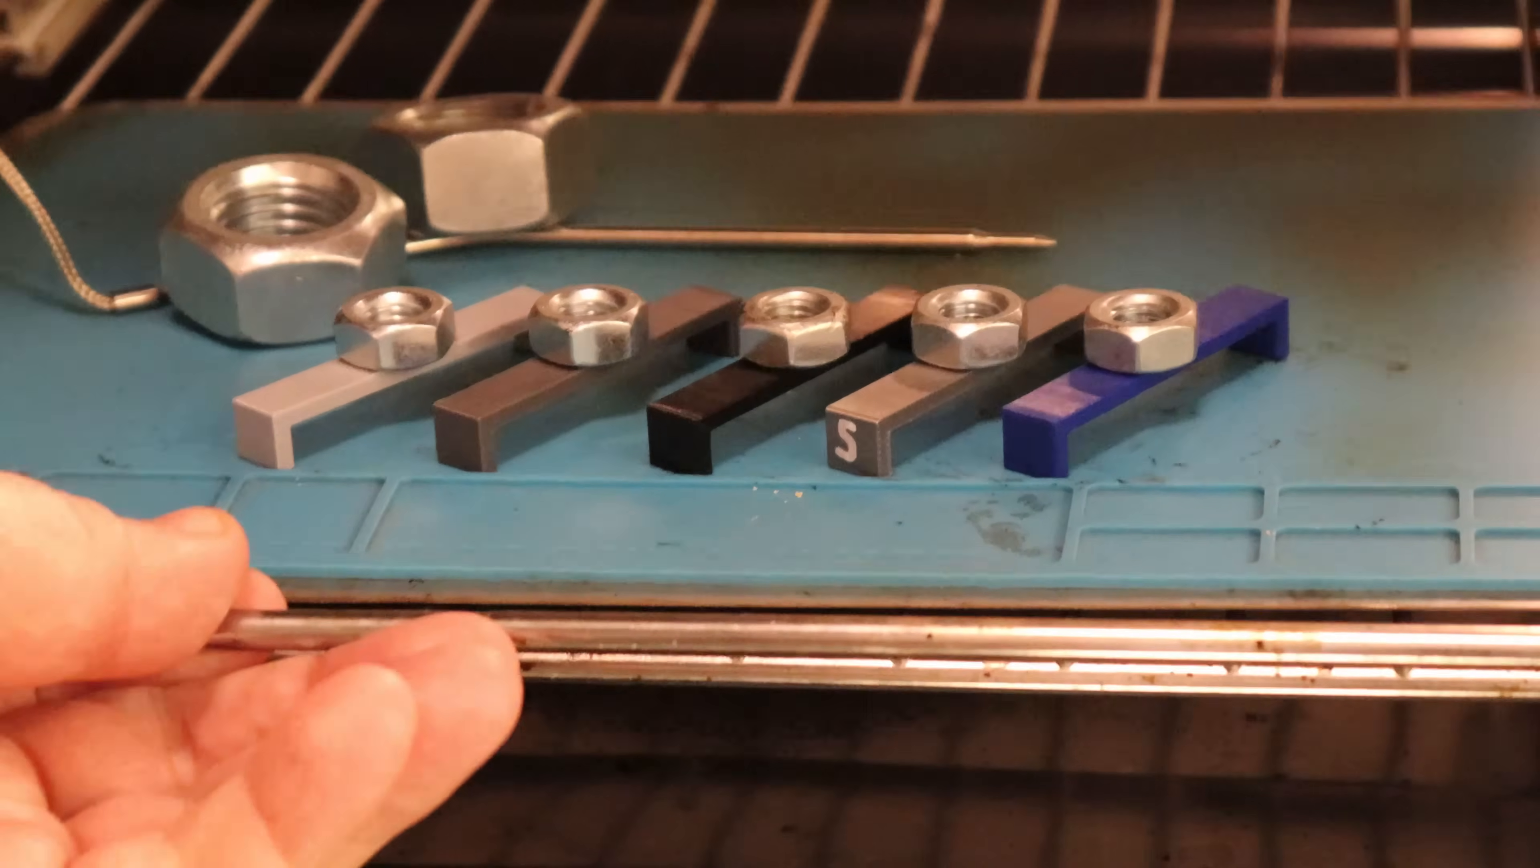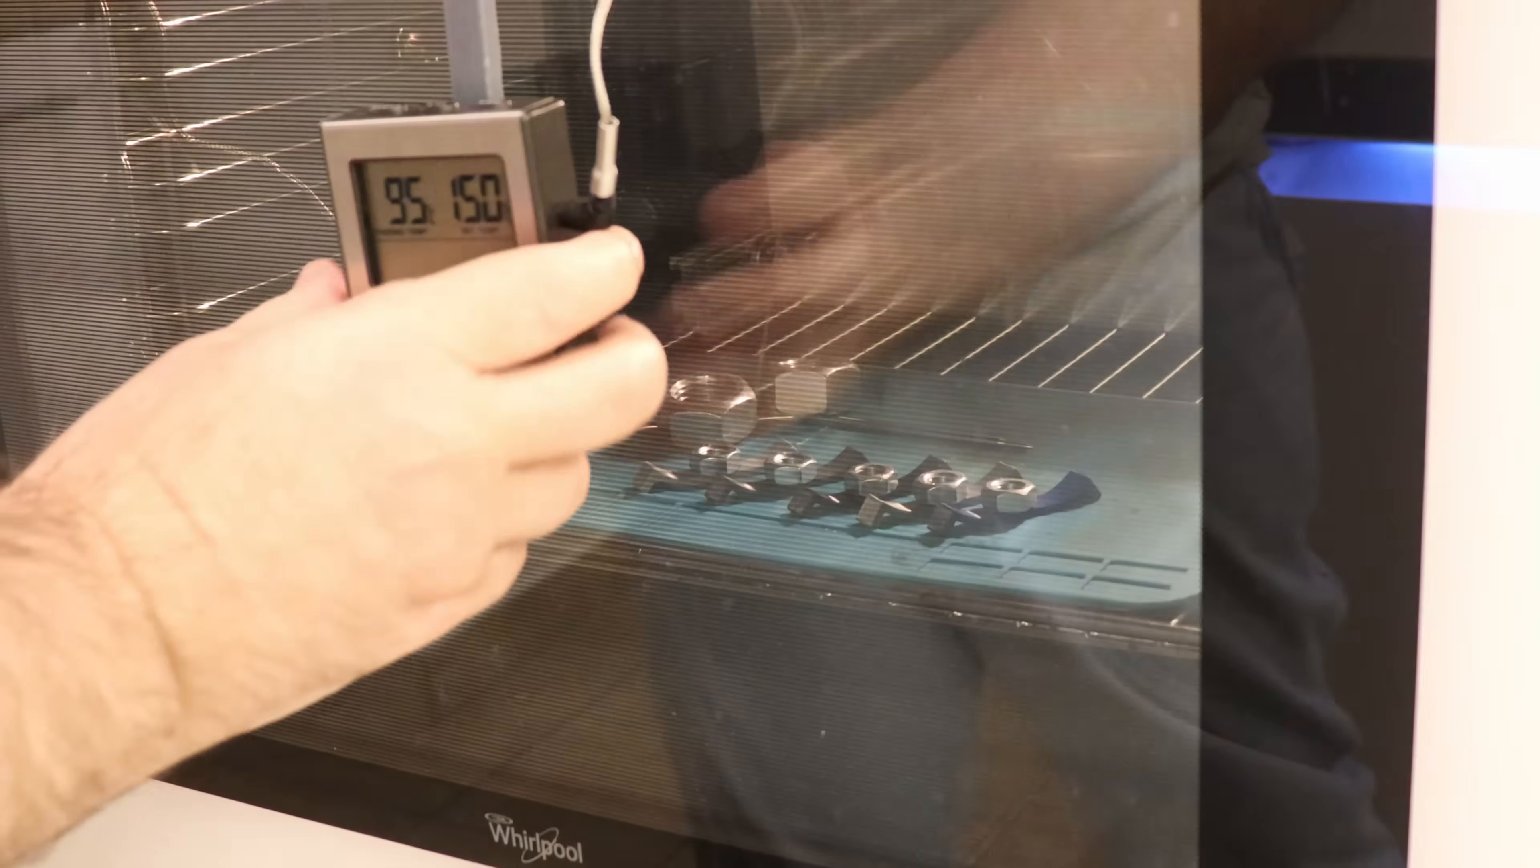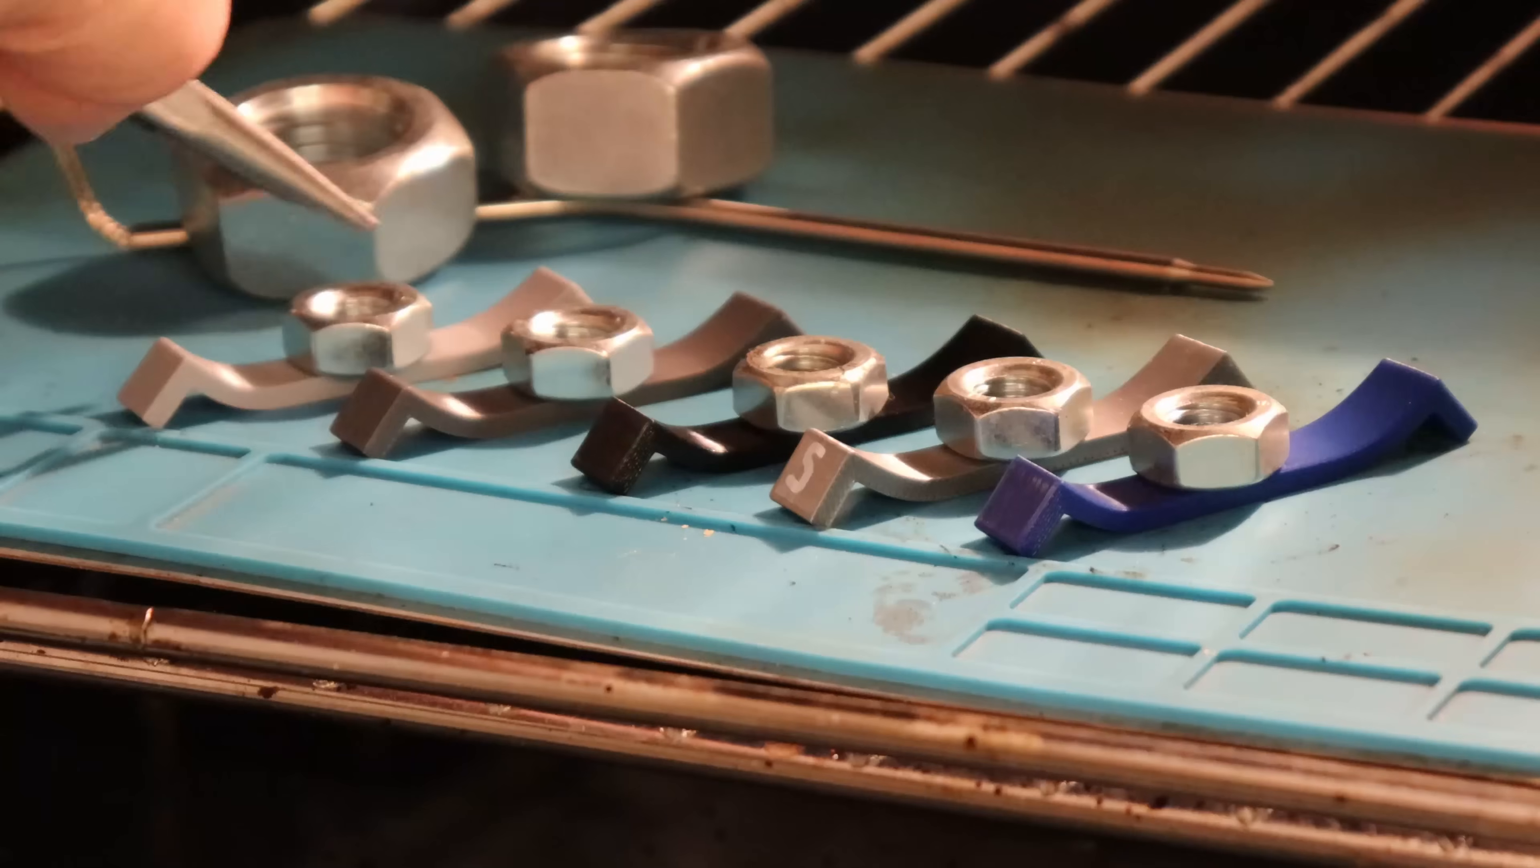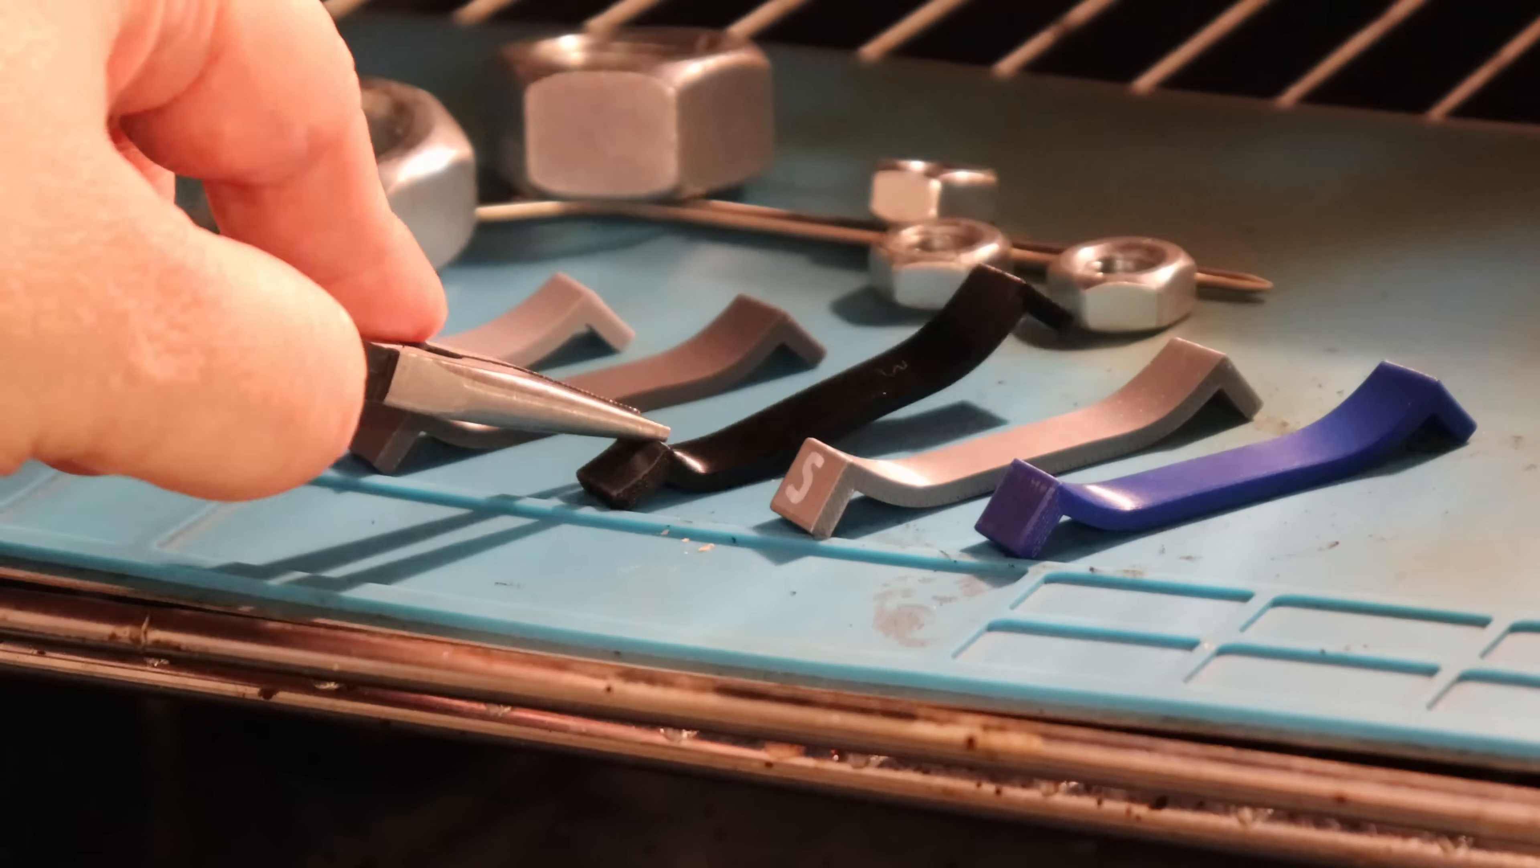Temperature test in the oven, where I want to record the temperature of the first deformation. And these materials started to deform at around 63 degrees Celsius, which is typical for PETG materials, a little bit below it. The average is actually 66 degrees Celsius, and to the touch, there is no big difference between them.